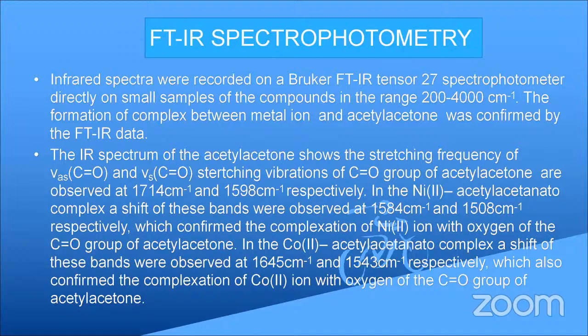After the complex formation with nickel, the shifts are observed at 1584 centimeter inverse and 1508 centimeter inverse respectively, which confirm the complexation between the nickel and the oxygen of the carbonyl group of acetylacetone. In the cobalt acetylacetone complex, the shifts are observed at 1645 centimeter inverse and 1543 centimeter inverse respectively. Here, from that band, we discover the complexation between the cobalt and the acetylacetone complex.